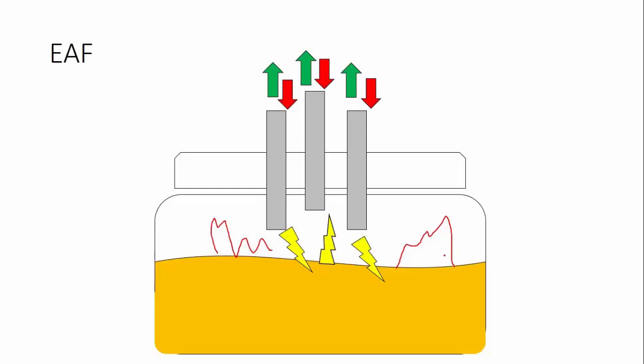Let's say plastic, other metals, whatever it is, starts floating on top of the molten steel. As the melting process continues, the electrodes can go up or down depending on the part of the cycle. At the beginning, the electrodes have to be near the metal, and then as the metal starts to get molten, the electrodes can go up or down depending on the power that should be delivered or how much heat the furnace can resist.